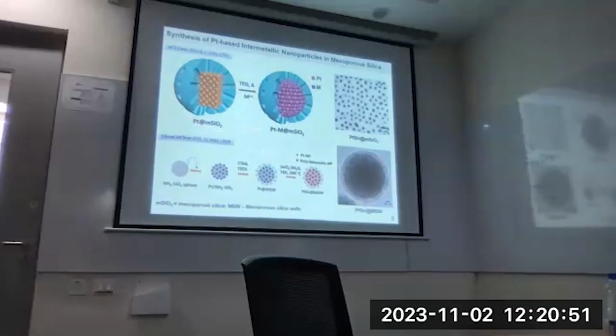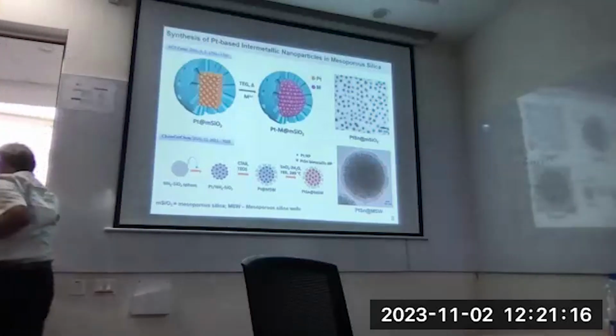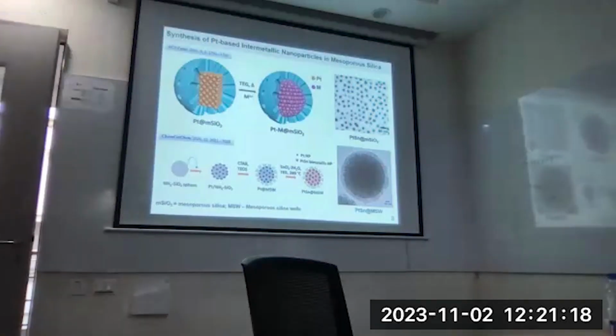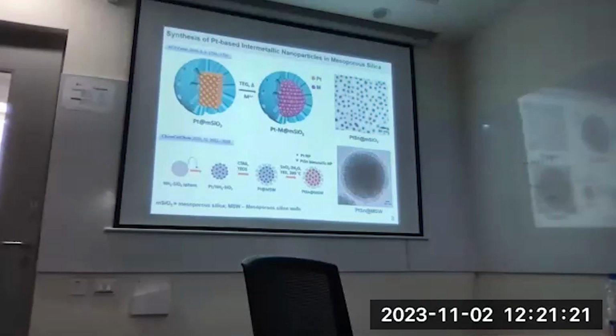There is another. This is one route. So around each of these, the core nanoparticles are around 20 nanometers. But we can make it smaller. This is around 4 nanometers. Okay, and each of them have different. So when you have a bulk metal, the melting point of the bulk metal is going to be around 1000 degrees for the particular combination of metals. When you make it nanoparticles, based on the size, its melting point is going to change. But this silica shell provides sufficient thermal stability so that during the reaction they don't coalesce, they don't become larger particles, and they can be good catalysts.